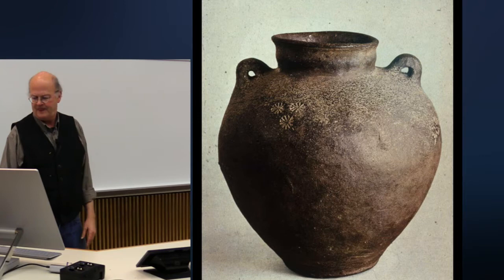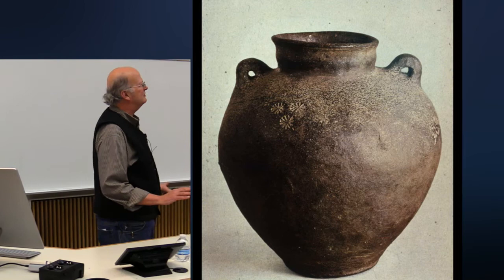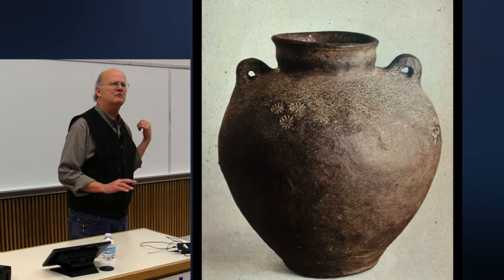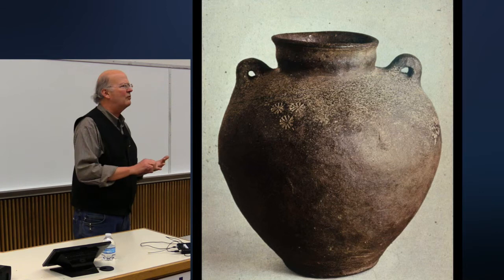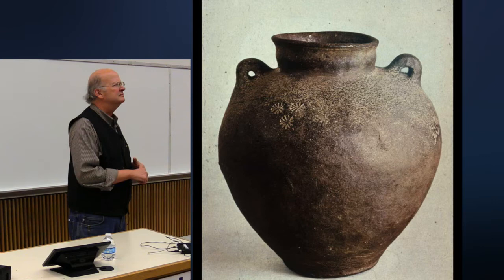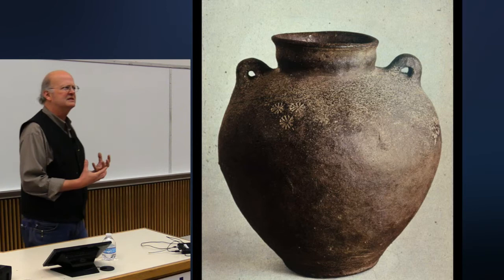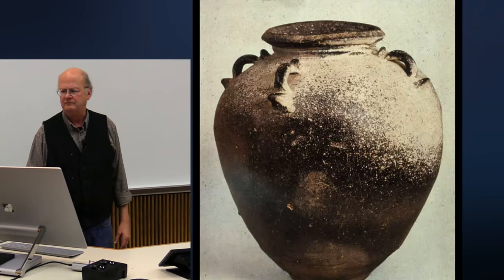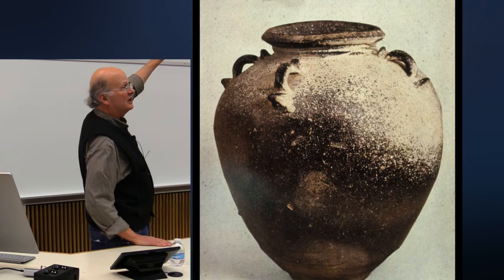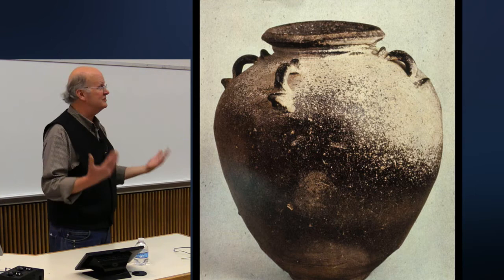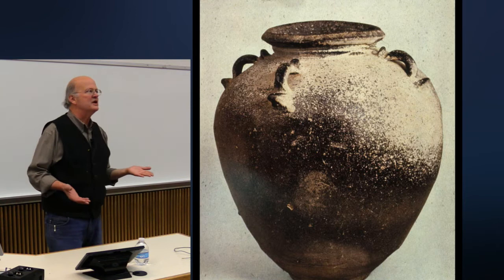I should point out, too, that when I started investigating this, I hadn't seen black pots like this, nor had I ever made any that were black like this, and I didn't really know what was going on. And I was speculating about what it is that they were using for colorant. It felt dense like porcelain, but it didn't have the color that we associate with porcelain. There are plenty of examples, too, where the surface is completely covered with the byproducts of combustion, which is, of course, wood ash. And wood ash by itself doesn't melt very readily in most cases.